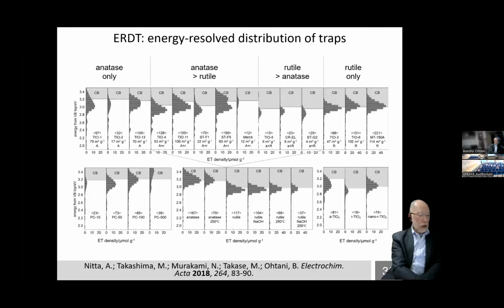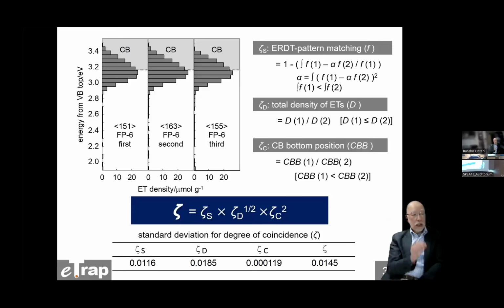And to check the similarity or identicalness of those ERDT CBB patterns, we quantitatively measured the similarity of samples. This is the result of one kind of commercial titanium oxide. For this RDB-PAS measurement, I asked the graduate student to take a sample from almost the same position in the same bottle. And he measured the same sample 3 times, and almost the same patterns could be obtained.